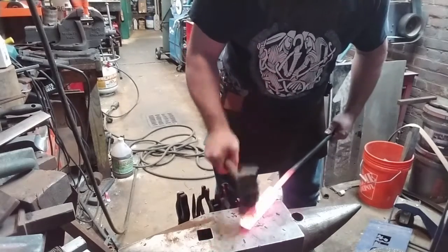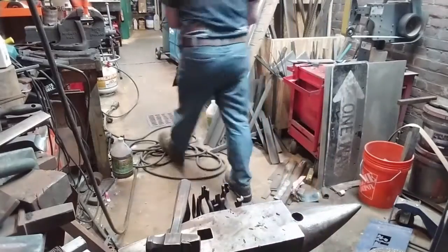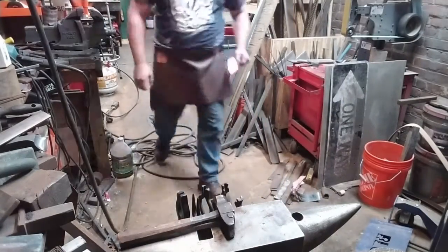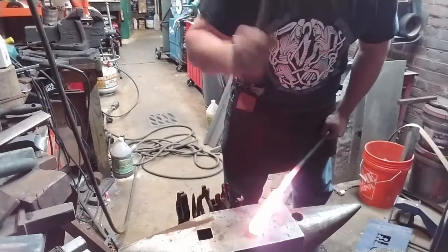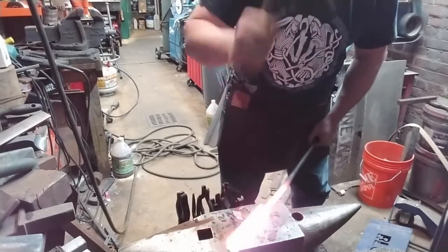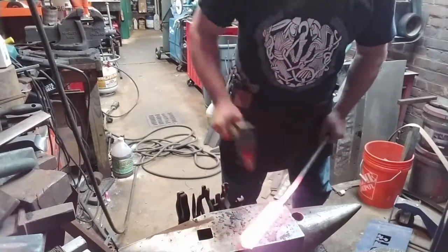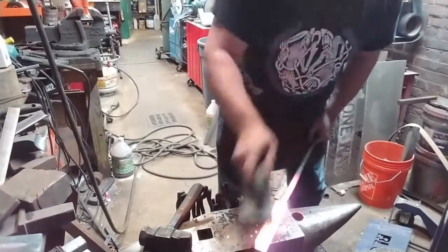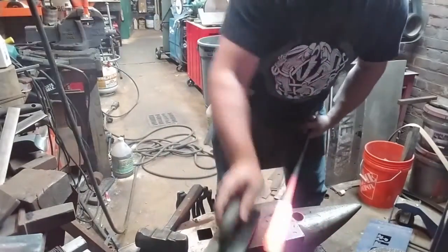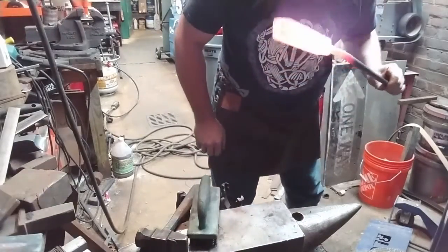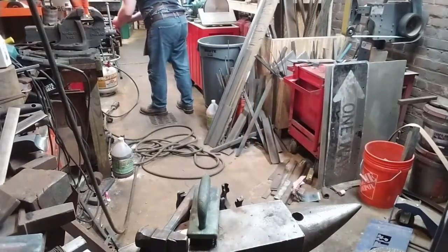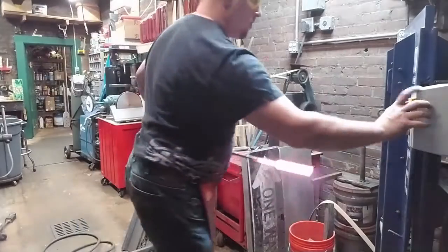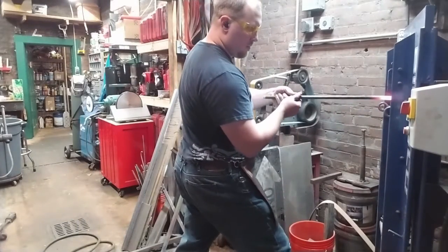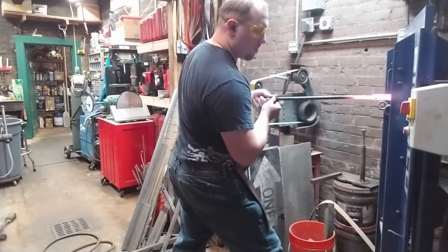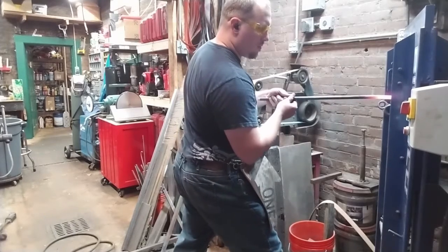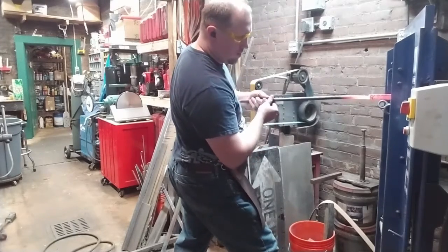I'm setting the weld. I'll be setting it a couple of times with light hammer blows on the anvil. It doesn't take a hard strike, and you can see the flux erupting out of the weld seams. That's a good sign. It's also necessary at this stage to keep the welds clean, just in case you might get any separation. You always want to do 3 welding steps: to tack, to set, and to blend. Or in this case, to set a little bit harder.